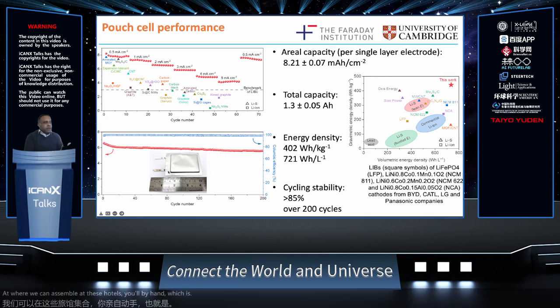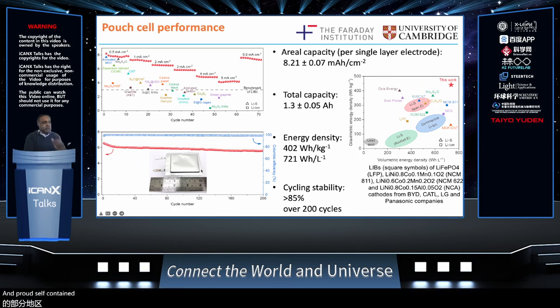This pouch cell contains six different layers, and we implemented our 1T MoS2 and achieved an areal capacity of 8.21 milliamp hour per centimeter squared. We made amp hour cells. This is not easily done in an academic laboratory.